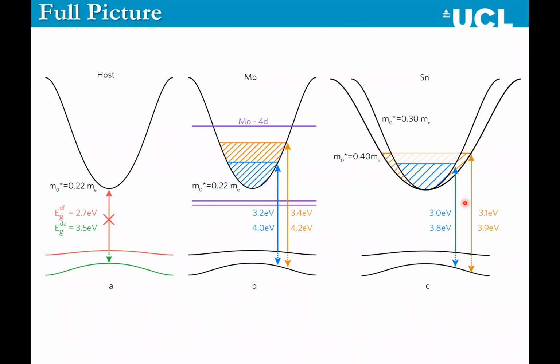And the schematic or the cartoon of what's going on we're left with is that as you increase the doping concentration in IMO, because you have no interaction between the molybdenum D states and the bottom of the conduction band, the effective mass doesn't change, so you maintain a higher mobility. But as you increase the amount of tin in your system, you get increased mixing between the tin S states and the indium S states, and you end up with a broadening of the conduction band minimum, leading to a tail off in performance and a lower mobility.